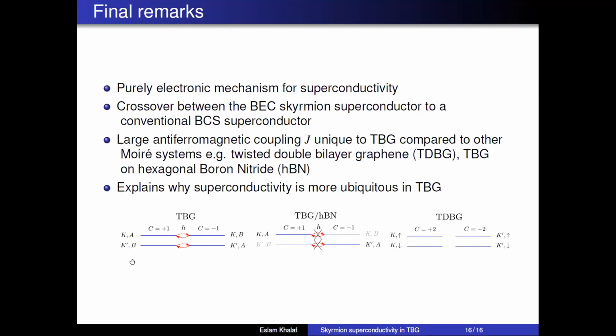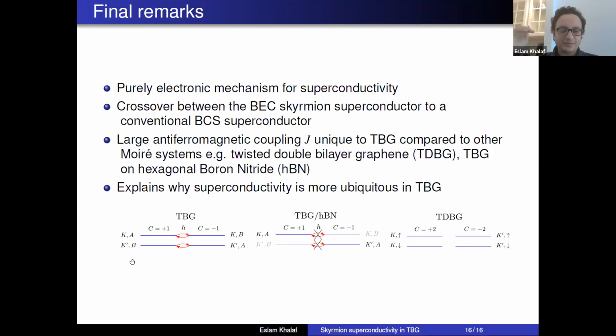But why did you choose to polarize the spin? Is there some numerical or experimental reason for that? So the main reason is, okay, so one thing is for simplicity, because the problem is a lot more complicated when you consider spin textures. And another thing is that we believe the state at half filling to be a spin polarized version of the state at charge neutrality. This is also suggested by, for example, these Weizmann experiments where they see these cascade transitions where at every integer filling, you polarize one flavor.